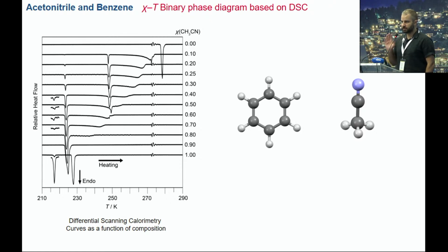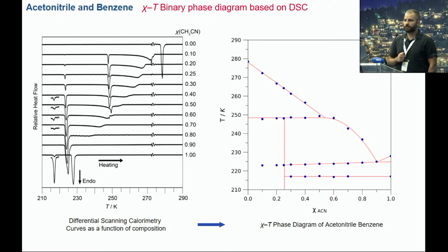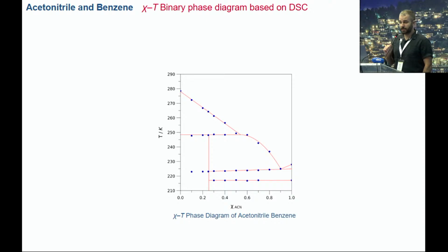Crystallization is arguably not a good idea because it's a kinetically driven phenomenon. Melting is more thermodynamic. So here I present the melting curves. If we take these melting curves, look at the minima, and plot them, we get a phase diagram. Immediately, it becomes clear that this phase diagram is not as simple as a single eutectic and just a mixture. This phase diagram is very rich. That tells us that there is a lot going on in this binary mixture. However, we don't know what.